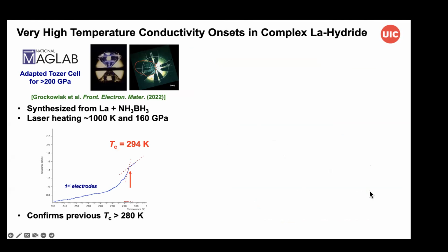The goal of this experiments, and the goal of this was to do careful measurements of magnetic field shifts and the Meissner effect. And in these experiments, we found that in this one experiment that was quite intriguing, an initial TC with a kink here, or evidence for some kind of behavior change in conductivity around 294 Kelvin, consistent with what we found in earlier experiments done with lanthanum and ammonia borane as the hydrogen source.